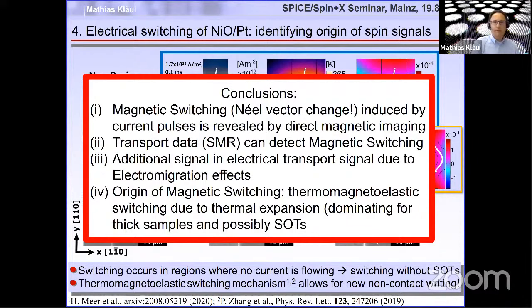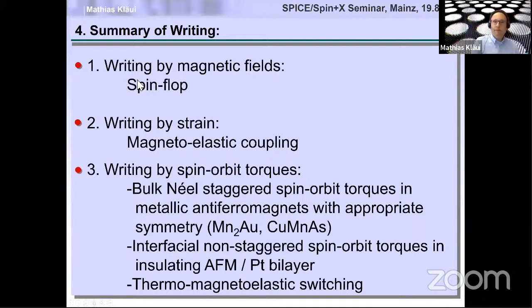And so to sum this up, we can write by spin flop, we can write by strain, but most interestingly, we can write by currents due to spin orbit torques, either bulk or interfacial, and thermomagnetoelastic switching. And the nice thing about thermomagnetoelastic is that it's non-contact. We actually don't need the current to flow through your device. So you can do this with a laser. You can do this by non-local heating. So there are a lot of possibilities that might be due to this non-local possibility of the thermomagnetoelastic switching.